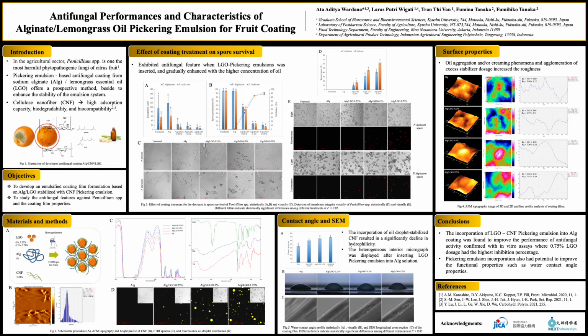Finally, the conclusion of this study: the incorporation of essential oil cellulose Pickering emulsion into alginate coating was found to improve the performance of antifungal activity, and it also had the potential to improve functional properties such as water contact angle and surface properties.